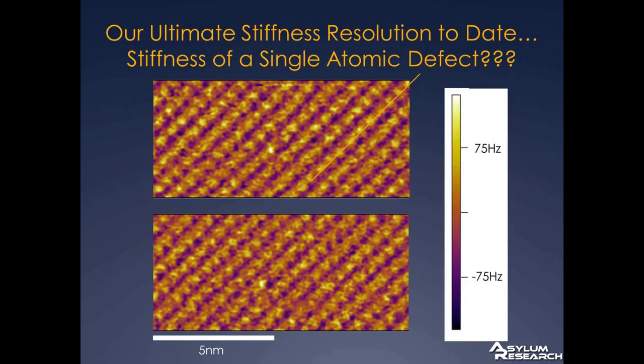You can see that in the valleys that I've illustrated with this little line here, the second mode is measuring a higher stiffness, which makes a certain amount of intuitive sense. And on the peaks, along, say, this line here, it's measuring a lower resonant frequency, which means that it appears to be softer. If we draw circles around the defects that were in the topographic image, we can see that there's also contrast in the stiffness channel, and in fact these single atomic defects appear stiffer to the second mode.